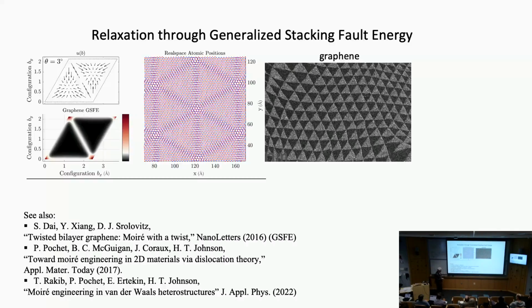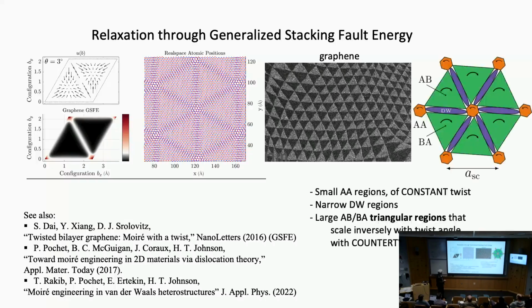Okay, so this is the pattern that you see experimentally, up and down triangles. And here's the picture that you should keep in mind. The pattern that you see here in experiment and in theory consists of these large triangular regions. Those are the so-called AB or BA regions, which are equivalent by symmetry. They're separated by these thin lines, the domain walls. You see these thin lines here in the theory. You don't see them in experiment because they're just too narrow on this scale. This scale is hundreds of nanometers, maybe microns.